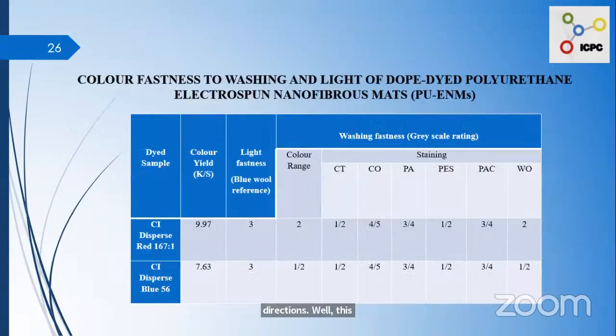So this is the table which shows the color fastness to washing and light for the optimized dope-dyed polyurethane electrospun nanofibrous mats with both dyes at optimum conditions. These results show that the overall color fastness of the dope-dyed polyurethane nanofibers was not very good. However, the color fastness of polyurethane electrospun nanofibrous mats was good when dyed with the same dyes by the pad-dry-cure method. So this ultimately shows that the dispersed dye is embedded properly into the polyurethane polymer when doped in a solution. This may be improved if the doping is carried out in the molten polymer instead of the polymer solution.